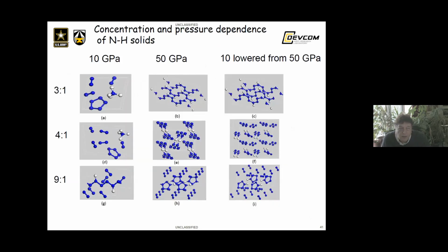Here are results for the structure prediction after evolution of 150 generations for 3:1 ratio. So 3 nitrogen, 1 hydrogen, 4:1 and 9:1. So high nitrogen concentration system at 10 GPa and 50 GPa, both are evolutionary simulated. So both are results of evolutionary simulation. And these are not evolutionary simulation. They just took the high pressure phase and lowered the pressure from 50 to 10 GPa just by isotropic decompression.